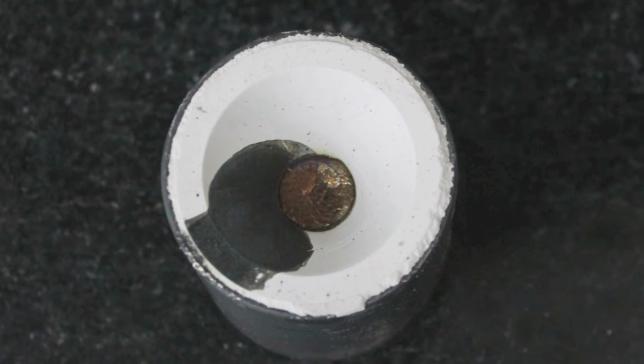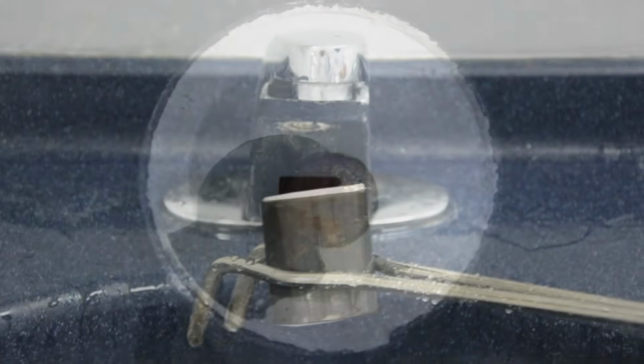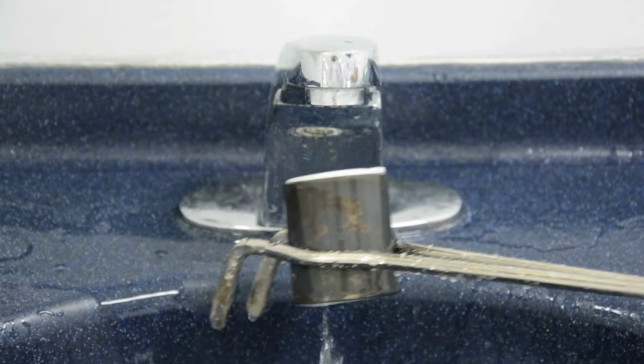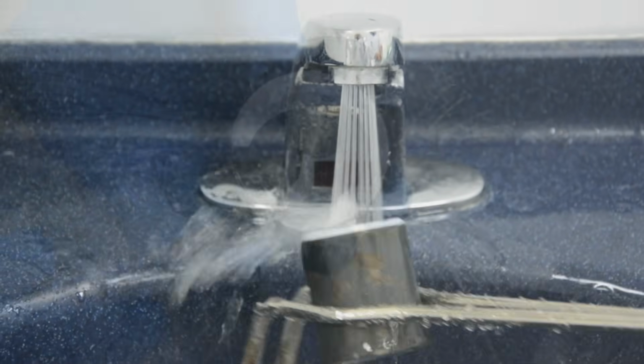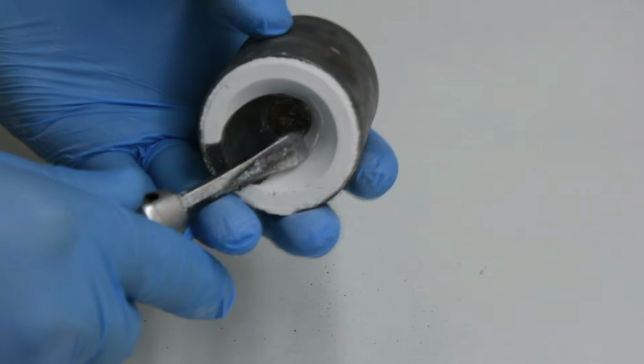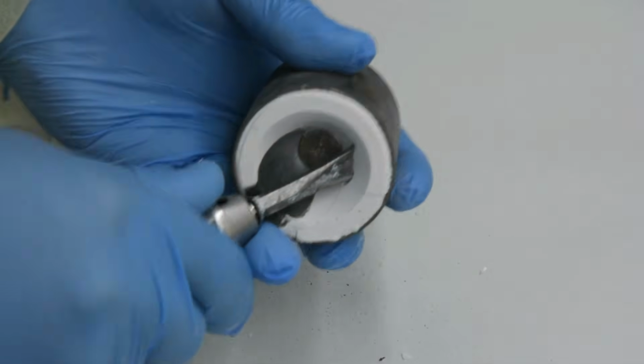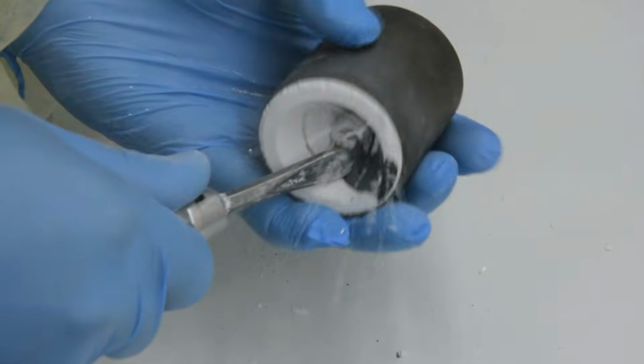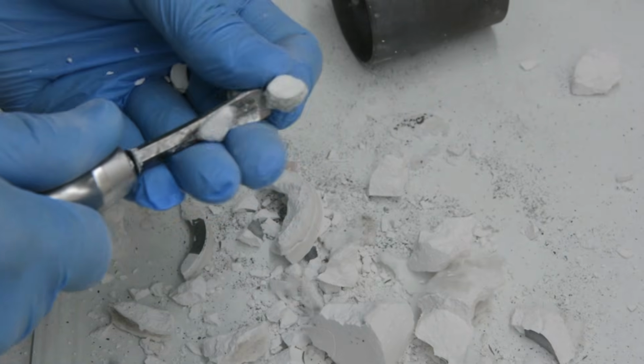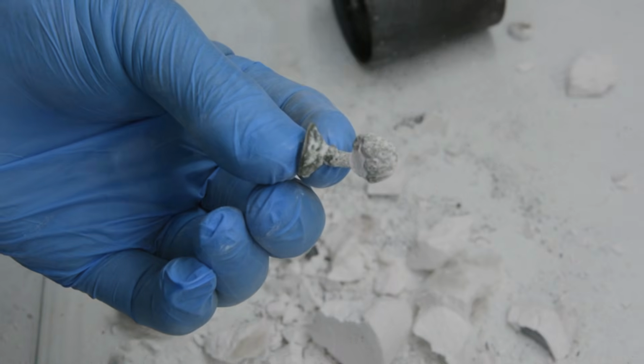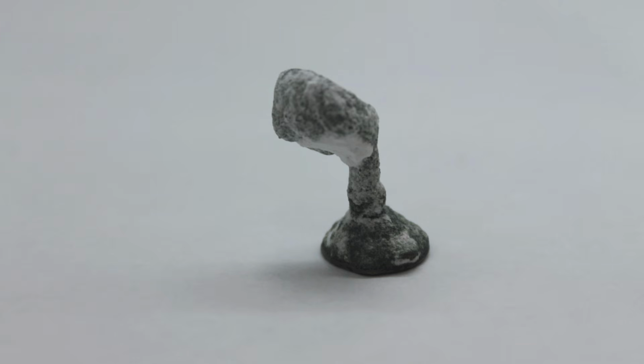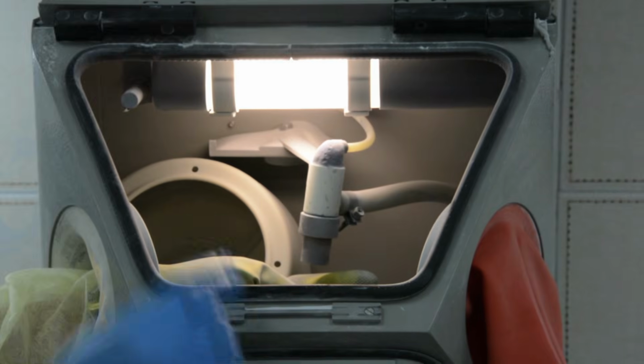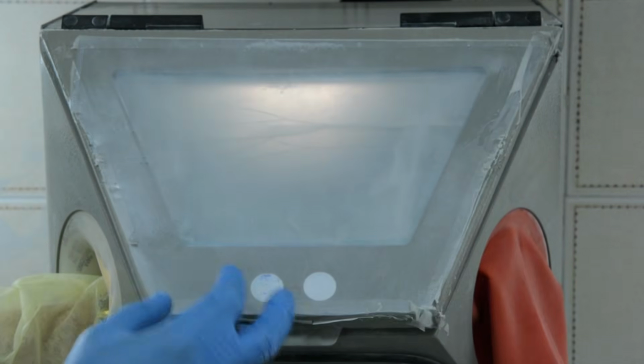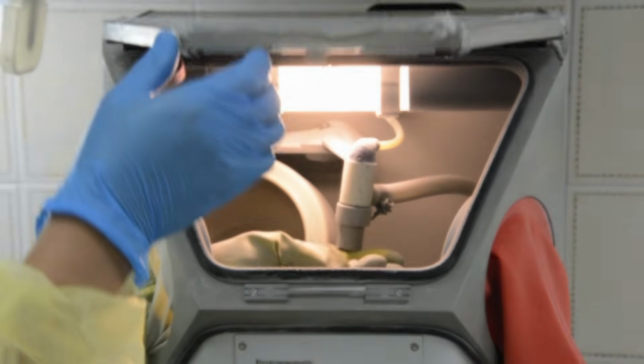After the red glow has disappeared from the bottom, the casting ring is plunged under running cold water. Trimming is done from the bottom end of the ring. The casting should appear smooth with a dull dark oxide layer. The oxide layer and other remaining particles of the investment should be removed by lightly air abrading all the surfaces.